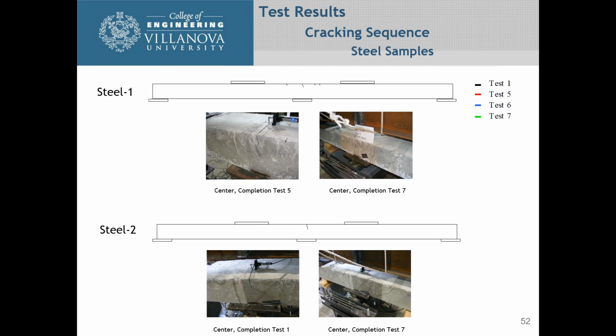after that you saw in both samples just a little bit of cracking in the negative moment region over the center support, which is what you would expect. At the end of test 5, which was after the 100,000 cycles of fatigue loading, you can see the steel started, the crack at the center started extending a little bit more, and there were cracks initiating at the bottom of the locations of where the load was applied. In the second steel one, really didn't see any increase in the cracking.